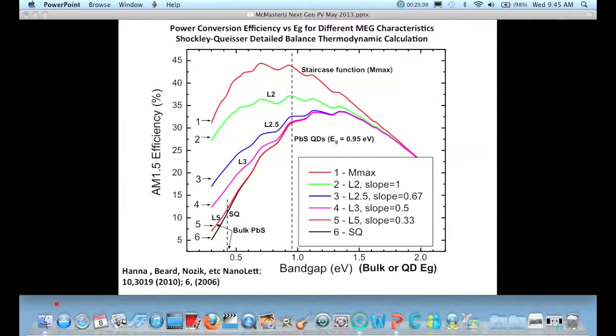And then for the various types of characteristics I showed, you get different Shockley-Queisser type plots. And you can see very quickly that in order to get a significant increase in the efficiency, you have to have an onset for this process that's at less than about 2.5 times the band gap. The best is the staircase. And this represents about a 35% increase in efficiency, which is quite good.